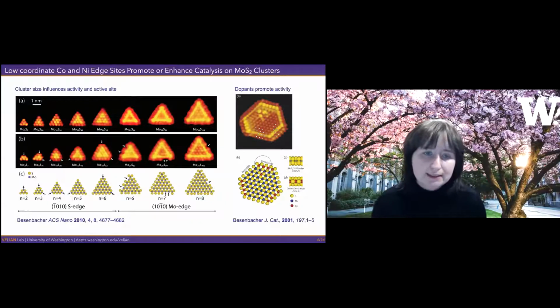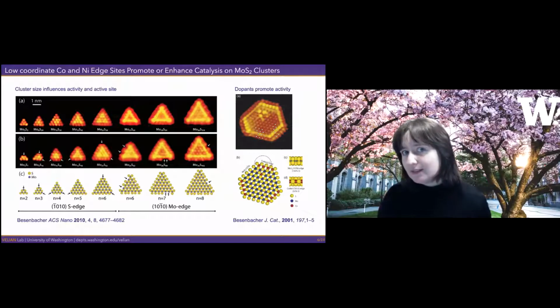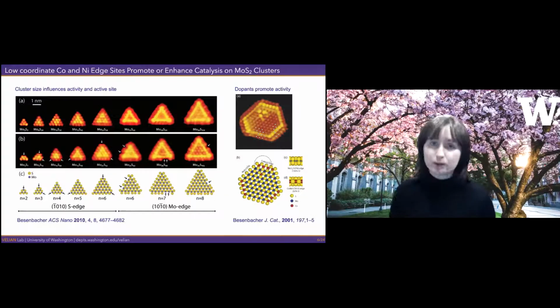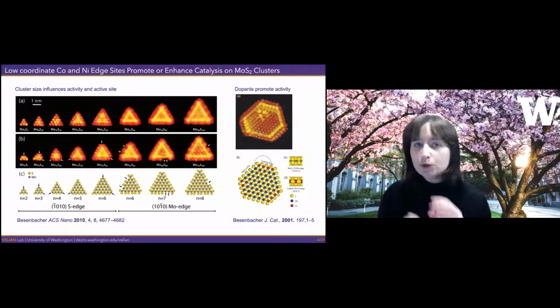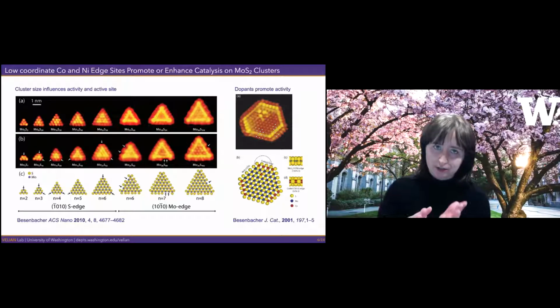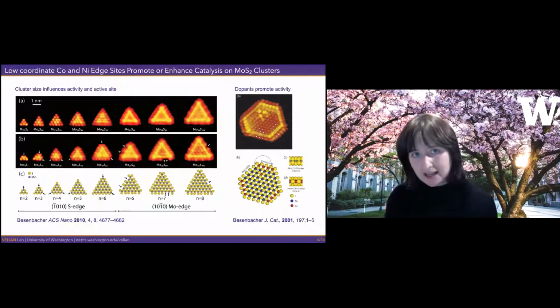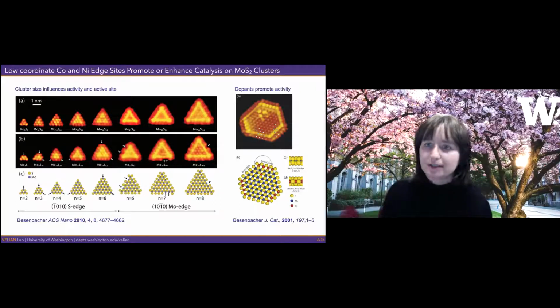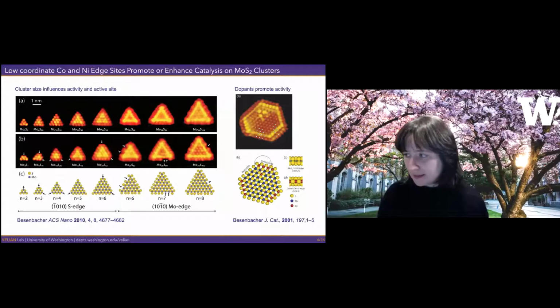And so what was discovered is that if you add even just a little bit of cobalt or nickel or other metals, as it turns out, a few things happen. One, you increase the activity of the catalyst by more than an order of magnitude. That's a lot. So something funky is going on there. And then importantly, you also change the selectivity of the reaction as you switch from cobalt to nickel. So the two additives, the promoters, essentially yield different products at the end, different selectivity for the products that are formed with respect to hydrotreating.